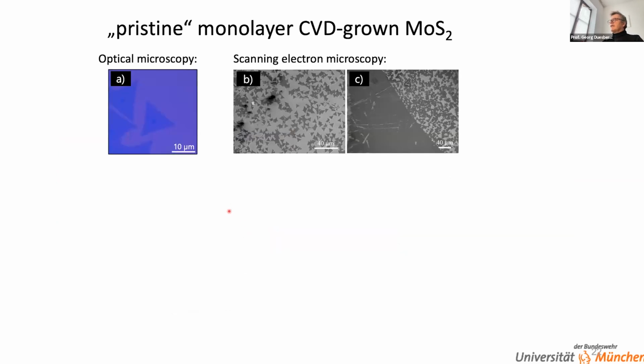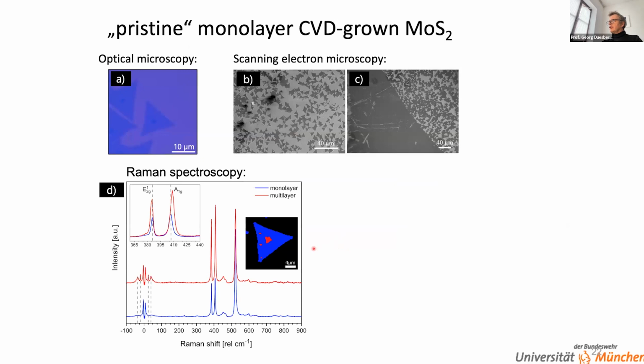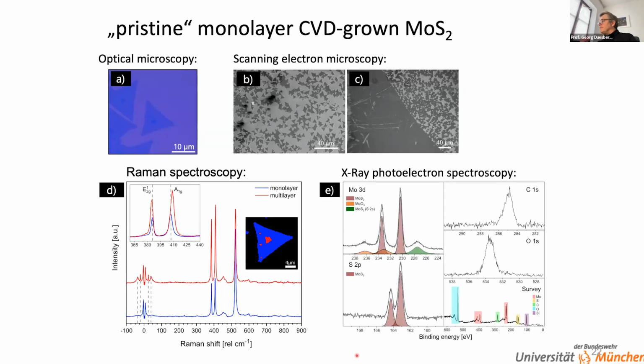Nevertheless, there's more initial characterization. We can look at the Raman spectra, and without going into details, we see the typical peaks for the Raman modes. We even see, for the multilayer region, the seed region, we can pick up the breathing modes and so forth. But we don't see any sort of contamination or anything like this on the pristine material. Same for the XPS. We pick up carbon, but you always pick up carbon. We also always pick up some oxygen. Nothing special to this material, except that it actually appears nice and clean.